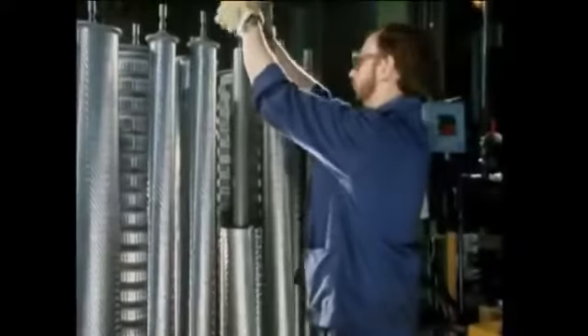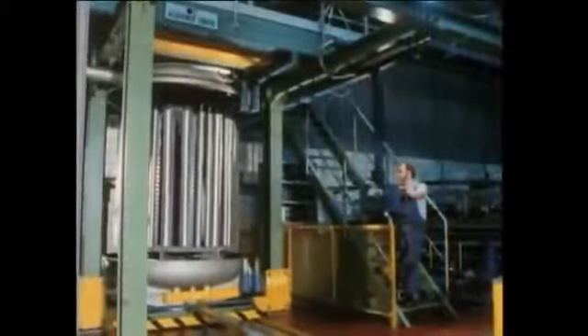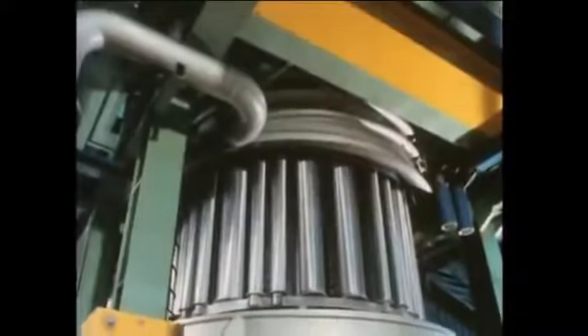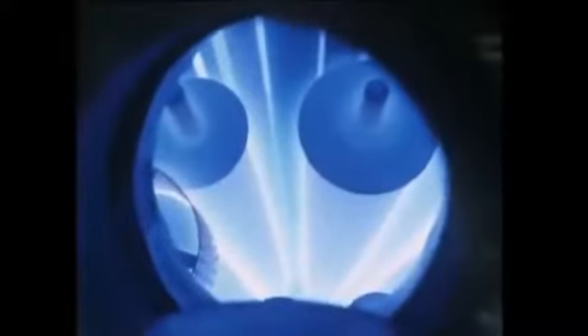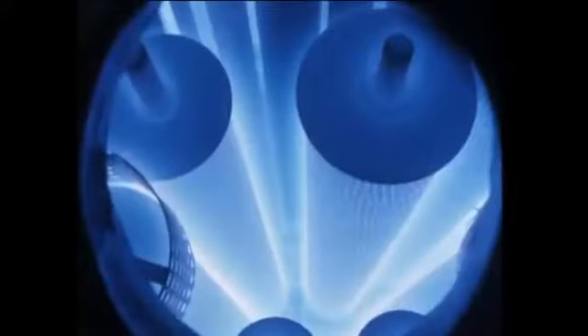These gear wheels need a hard-wearing and tough surface area combined with a softer ductile core. This fully automatic ion nitriding system achieves just that. It's a very clean process, with no washing needed or shot blasting necessary, resulting in a minimum of further machining. The low-pressure furnace atmosphere is a mixture of 25% nitrogen and 75% hydrogen, and with a voltage of between 300 and 1000, the gases become ionised. The gear wheels absorb the nitrogen to form a hard surface layer. This is one of the many examples of high-tech in the world of Ford tractor manufacture.